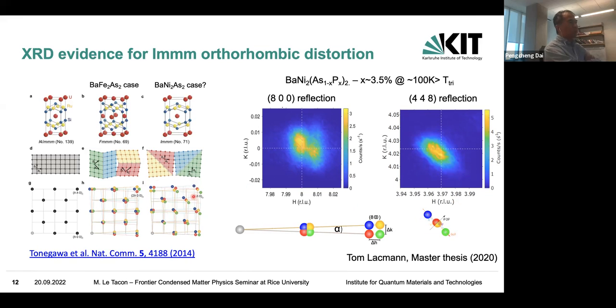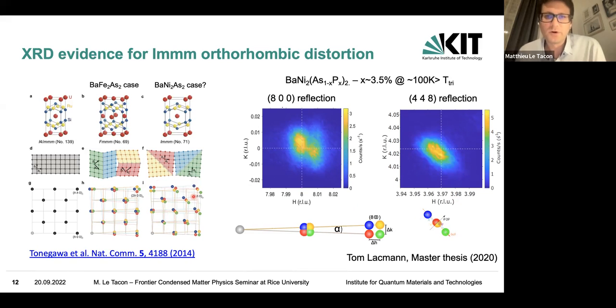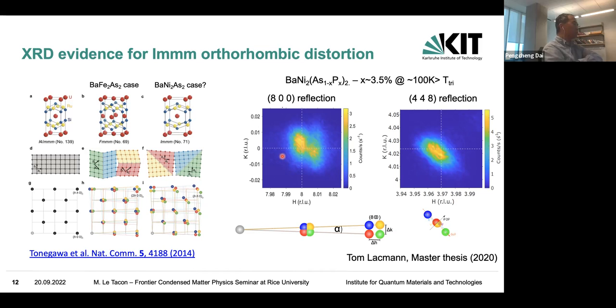Did you see temperature dependence of these peaks? This is a very, very small effect actually, and all this counting took a lot of time. So we had some scans as a function of temperature, just some cuts only. We don't have the full maps as a function of temperature. This was done on the four-circle diffractometer at home, and it took a humongous amount of time to get those. But yes, we do have some scans as a function of temperature, and we see the broadening. The bottom line is that if you really look at the parent compound, it's really hard to resolve this kind of splitting on the four-circle. On the doped compound, I think it was quite convincing, but it remains a very, very tiny distortion. I emphasize that because it was discussed last time, and it's also going to be important for the rest of the story.